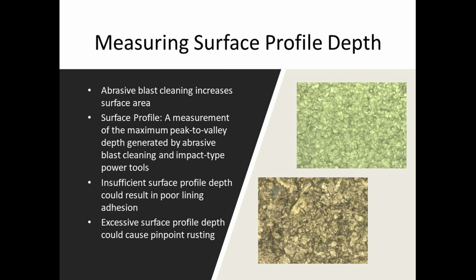Blast cleaning not only cleans the surface, but it increases the surface area. So we create a surface profile in the steel. And essentially, we want to be able to measure the depth of the surface profile because our specification typically is going to have a minimum and a maximum surface profile, and we have to stay in that range. So how do we determine that? We can't visually determine whether or not we've got the correct profile. We actually have to measure it.